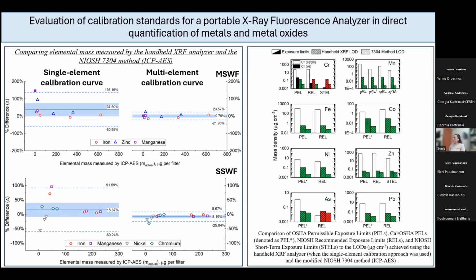And finally, this is a plot that shows the recommended and permissible exposure limits that were established by OSHA and NIOSH in comparison to the calculated limits of detection for the handheld XRF and the established NIOSH method that uses the ICP-AES.